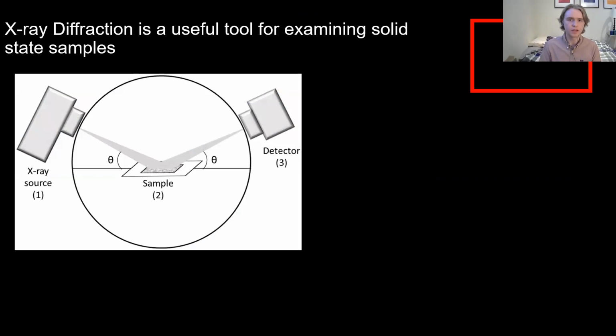So to check the specifications, the main tool that I used was X-ray diffraction. And X-ray diffraction is a very, very useful tool for examining solid state samples in particular. And it's important that we measure MOF5 in the solid state, because if the MOF is not in the solid state, well, then you really have ceased to have a MOF at all. Because they are these particularly set up frameworks, they always have to be in the solid state. And if you think you've gotten a MOF into a solution phase, well, then you've actually just lost the structure entirely. So X-ray diffraction is really, really useful for MOFs in particular.